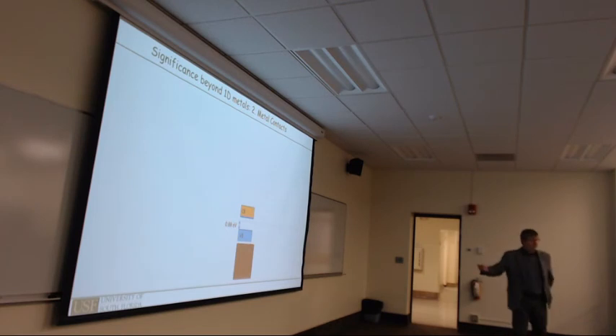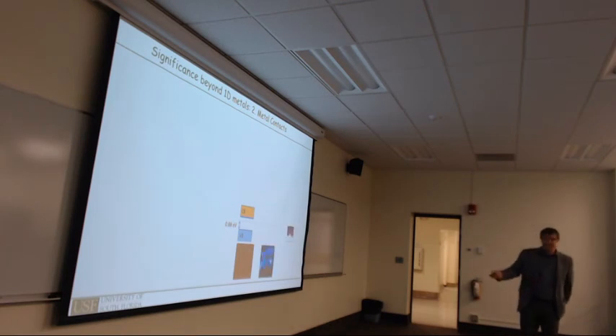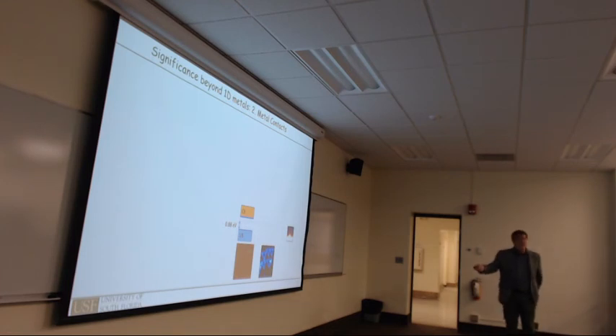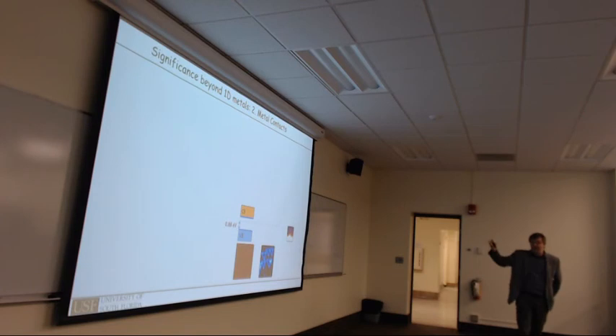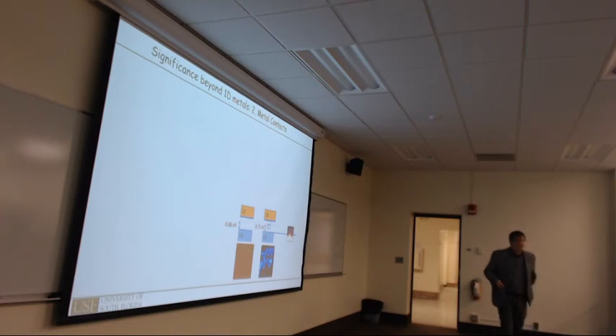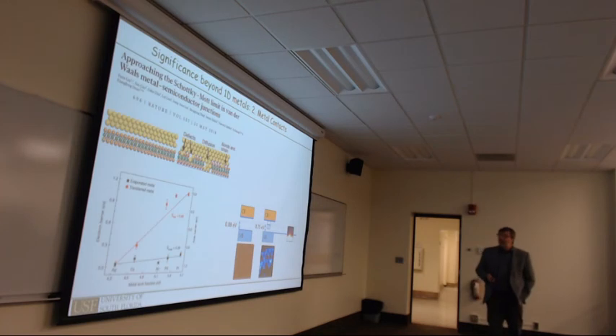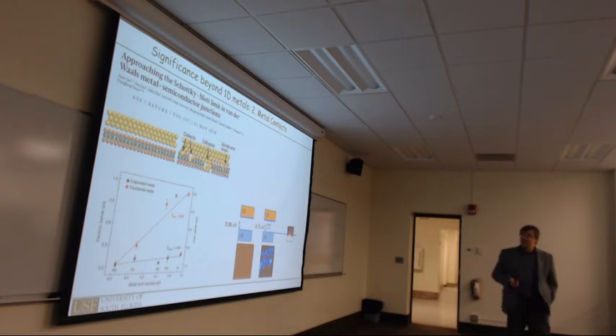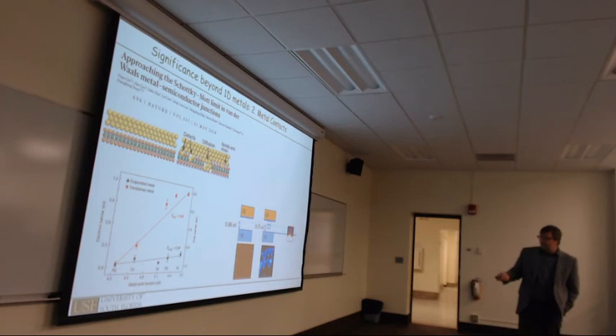However, if you deposit your metal, and your metal forms defects, then you get defect states, as we showed, within the band gap, and those defect states then will pin the Fermi level at the neutrality level of the defect, and then the position of the valence band maximum to the Fermi level becomes defined by the defect state in the material. This may be an issue for 2D materials, especially for molytelluride. We think that if you deposit metal, we get these grain boundaries.